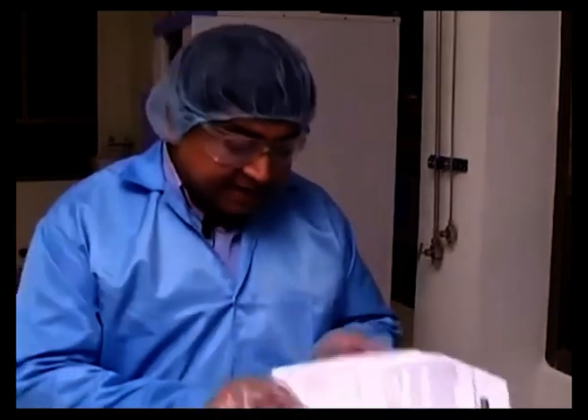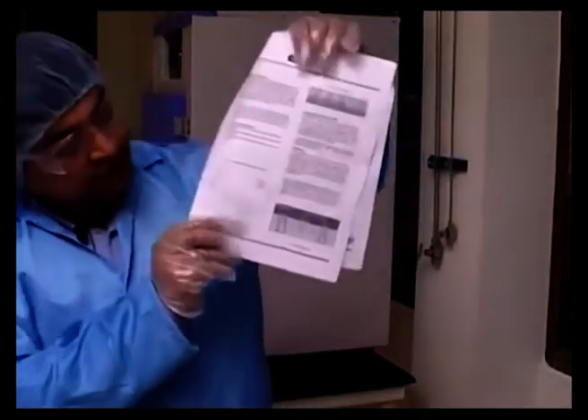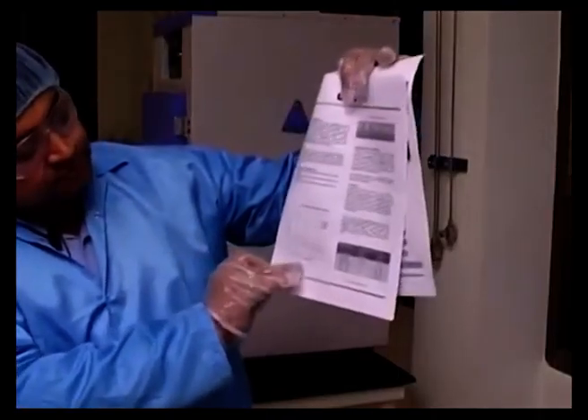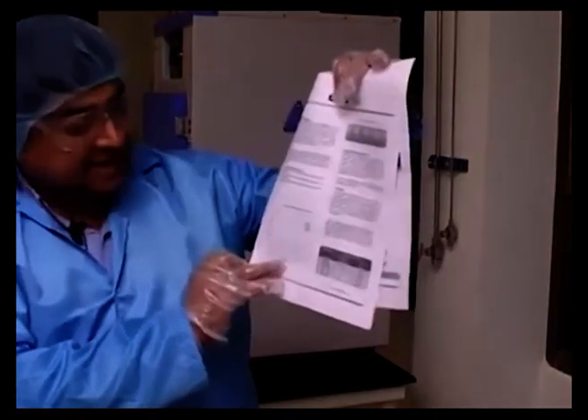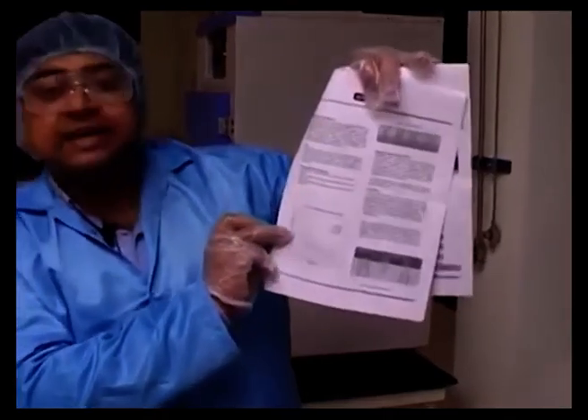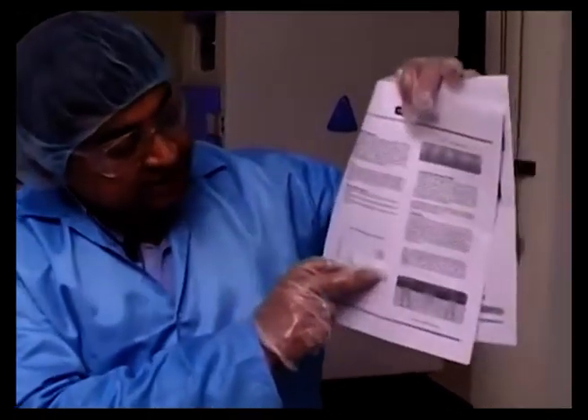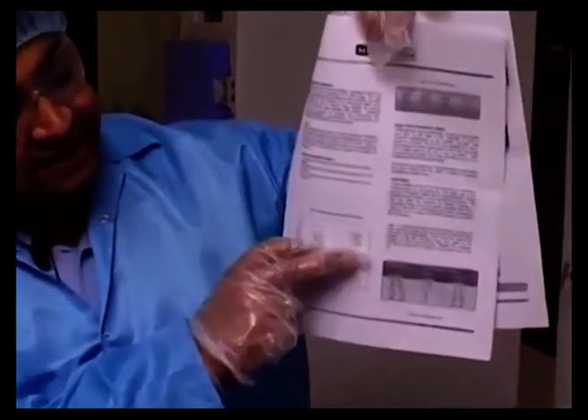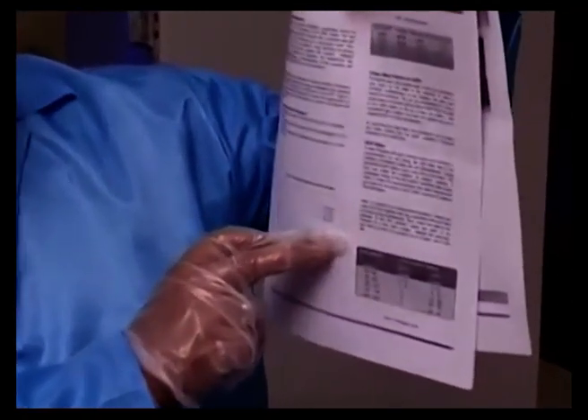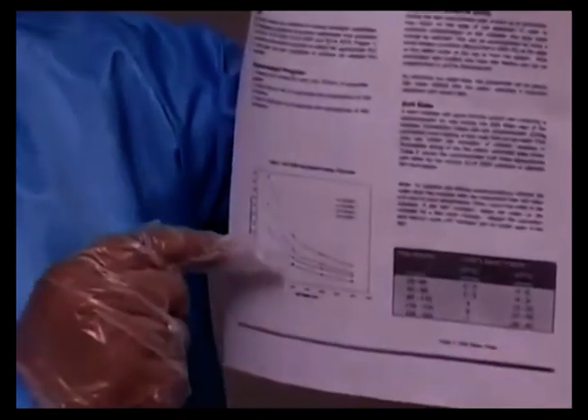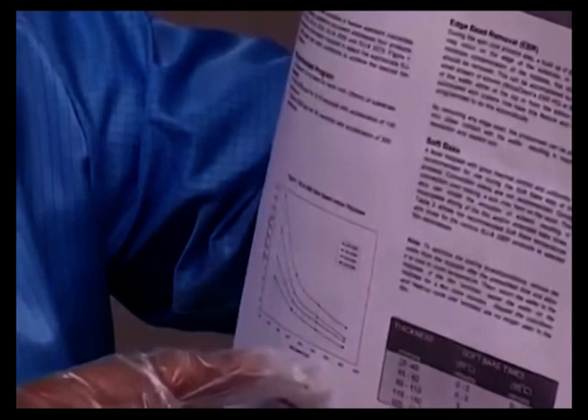And for doing that, if you look at this resist grade sheet, you basically get these curves which show the RPM on the x-axis and the corresponding film thickness that you will be getting. So when we are using a certain grade, which is mentioned in this table, SU8 2025, which is the lowest grade here, corresponds to the lowest curve. Corresponding to about 20 to 25 microns, we find that the RPM we would need is close to 3500 RPM.